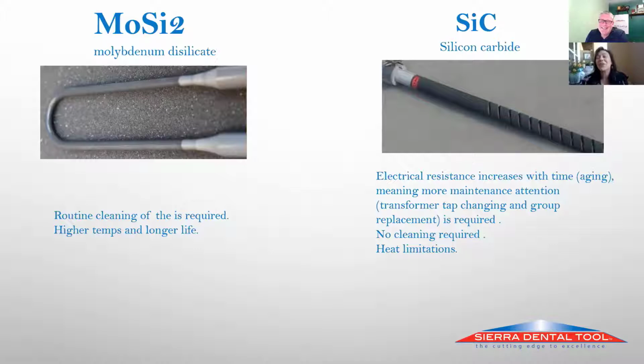So that's actually what it looks like on the heating element. And they can grow to be a pretty decent sized bubble. That is the silica burning off of your element, and that silica is actually needed to protect the heating element. It's also there to help the element conduct heat. So as we start to burn it off, the more bubbles are growing, the more you're deteriorating your heating element, it will start to lose its ability to conduct heat.